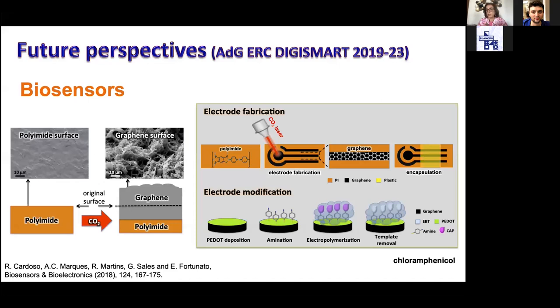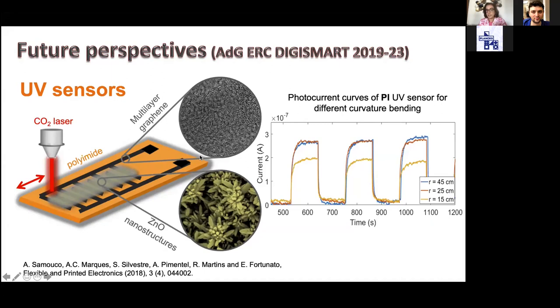Also, we are exploiting the same principle. In that case, the application is not a biosensor, it's a UV sensor. So we pattern the graphene electrodes, and we deposit on top of the electrodes some zinc oxide, and this is the result, for example, of a UV sensor.